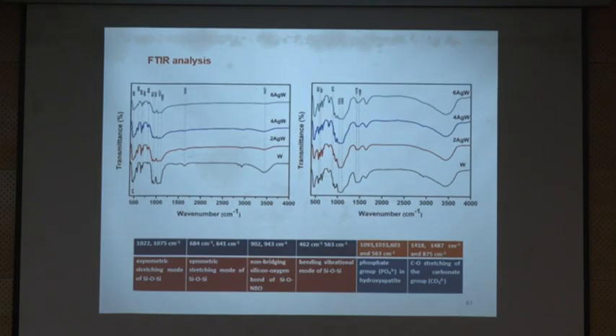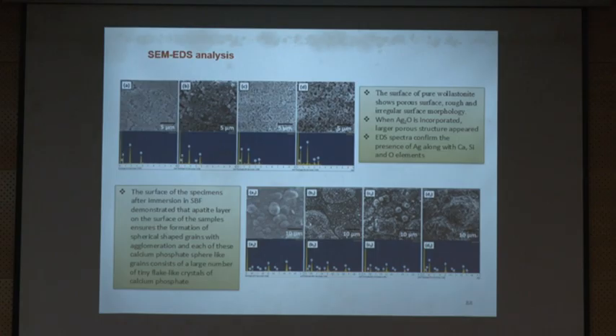So this is the XRD analysis, and you can see the growth of the layer on the surface of the sample, right? You can see the different morphologies. All these are the images recorded with SEM to confirm whether the material is active or not. So on the surface of the material, the hydroxyapatite layer will try to grow, and you can see with time it is trying to change. It is having different morphologies: flake-like structure, globe-like structure, then you know about the cauliflower type of structures. So we can see different morphologies.